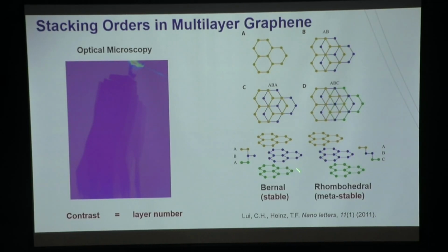One is known as Bernal stacking, and the other is known as the rhombohedral stacking. Bernal stacking is energetically the most favorable form of graphene stacking or graphite. You get a piece of graphite, about 80% of volume is going to be in Bernal stacking. Well, rhombohedral is less stable, but you still have probably like 10% of your graphite to be in this kind of stacking order.